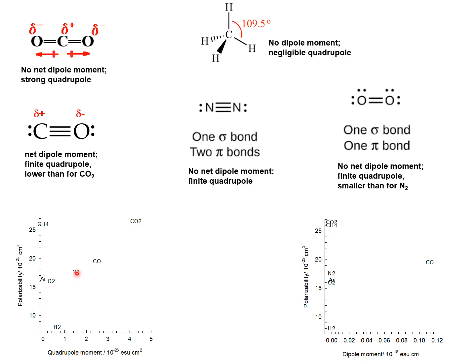We also note that the quadrupole moment of nitrogen is about a factor of 4 higher than that of oxygen. Of these guest molecules, only carbon monoxide has a dipole moment. For separating CO2 from methane, we can exploit the large difference in the quadrupole moment between CO2 and methane — methane has a zero quadrupole moment — by electrostatic interactions with the extra-framework cations. Similarly, the selective adsorption of nitrogen from mixtures with oxygen is achieved because of the large quadrupole moment of nitrogen.